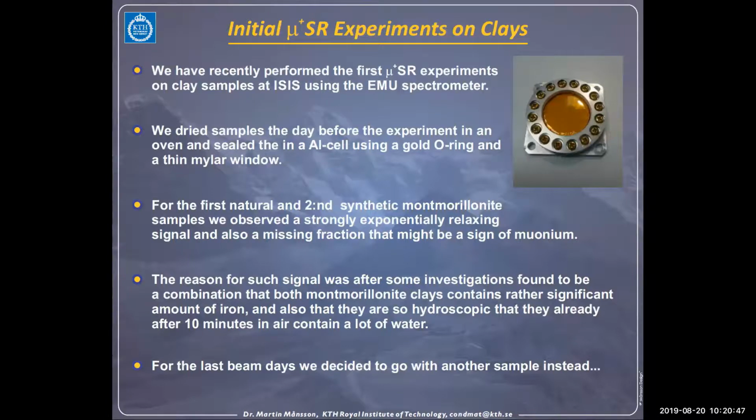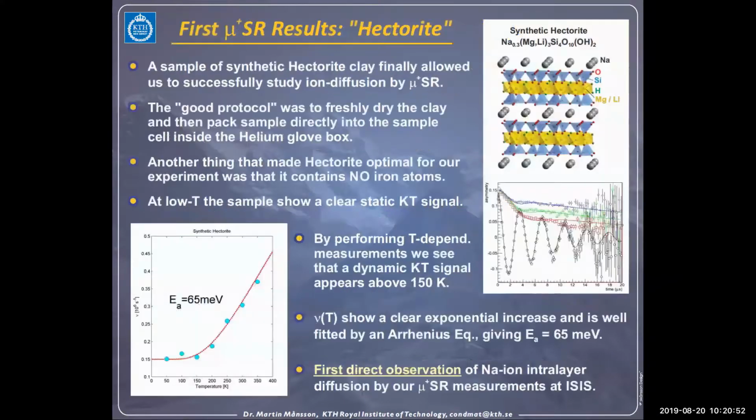We said, okay, what should we do? We only had one beam day left. So we focused on something else, a synthetic hectorite clay that was better controlled. We found a good protocol where we really dry it and pack it immediately after drying, because even within 10 minutes it starts to suck up moisture from the air.